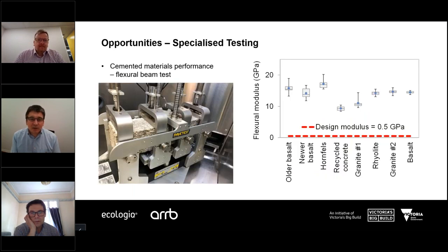So as we said earlier, in design, a cemented subbase or a bound material might be the application for the recycled aggregate, and we need to understand the properties of that cemented material. The newer specialised testing we can do is a 4-point bending flexural beam test. This enables us to measure not only the crushing, well, normally we'd measure just crushing strength, as in unconfined compressive strength, UCS. This new test enables us to measure the flexural strength of this cemented material. It also enables us to look at the modulus, flexural modulus, and that's a design input, as well as the fatigue performance.